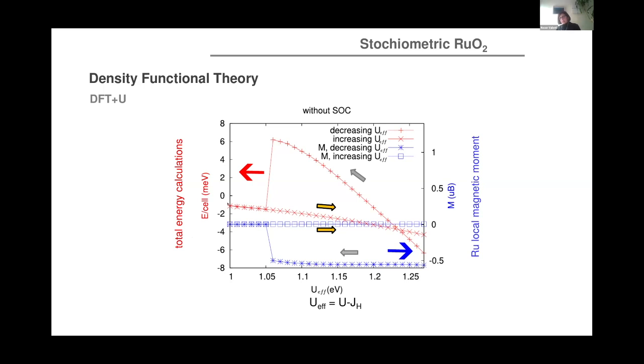As you can see, if we go now from the left to the right, by putting larger and larger U's, the energy goes down, but the magnetic moment of ruthenium remains 0. So the system doesn't magnetize even if one goes to very large U effective, which is U onsite minus Hund couplings.